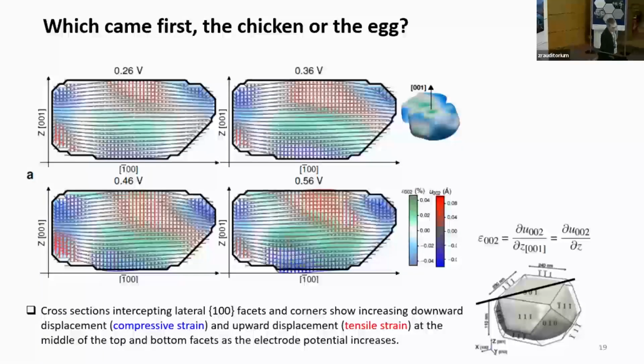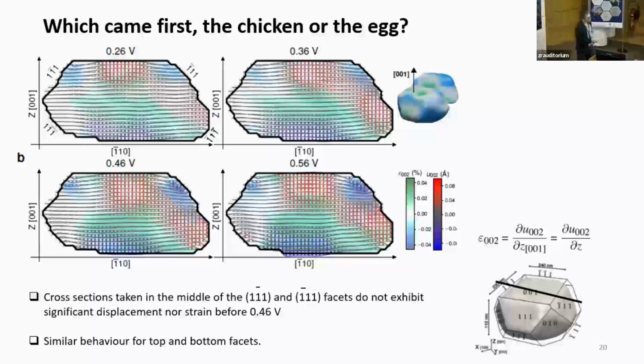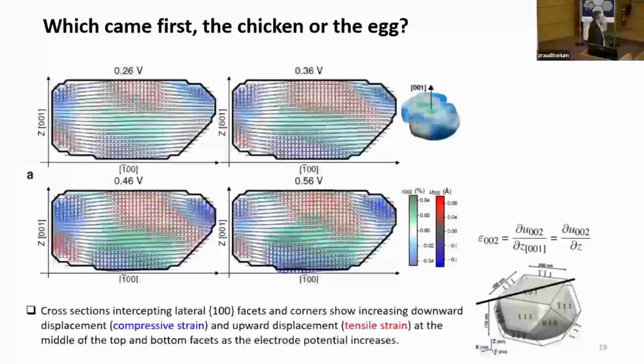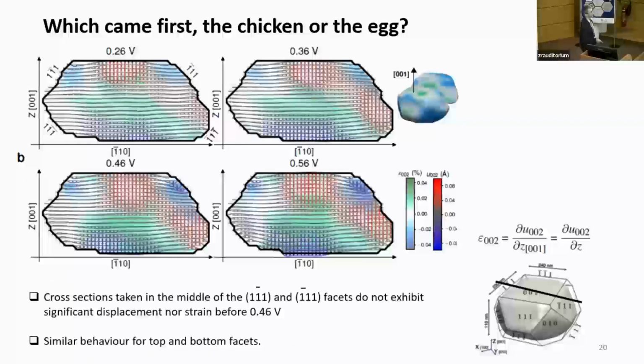Now, if you do the same, for example, here, so you first cross one edge atom, the very same top facet, and another edge atom. Already, by comparison, you see that there is much less heterogeneity, and things start to develop at 0.46. So you need to get to a higher potential for things to start to move. So in our opinion, that was a good proof that essentially the corners are driving the game, and they are causing the expansion of this top and bottom facet.